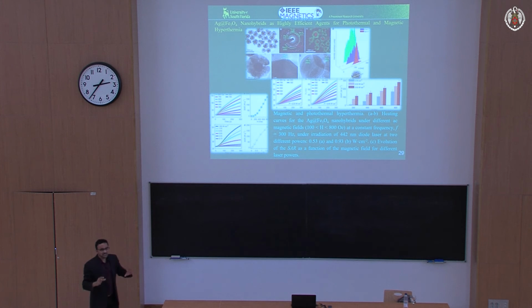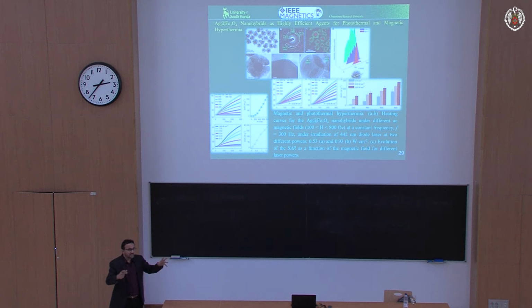And the idea here is to expose both the surfaces for functionalization. Gold, for example, has its well-known thiol chemistry. You can attach various things to it, and also it's biocompatible. So in principle, you have both the surfaces exposed. It's easy to make core shell. In other words, you have magnetite coated with gold, but then you're losing the surface of the magnetite, right? So in this case, by making these hybrid structures, you're making both the surfaces exposed for functionalization.